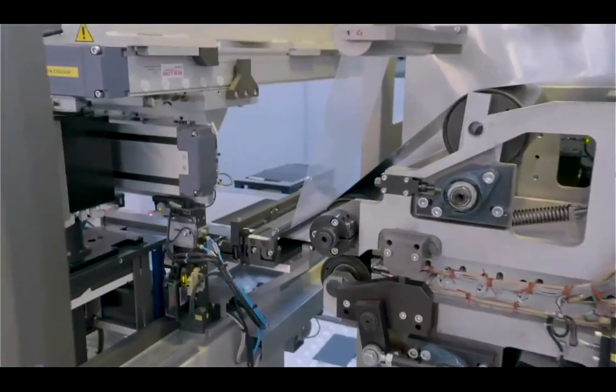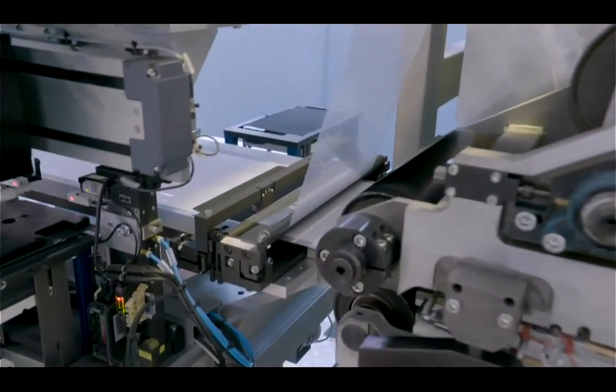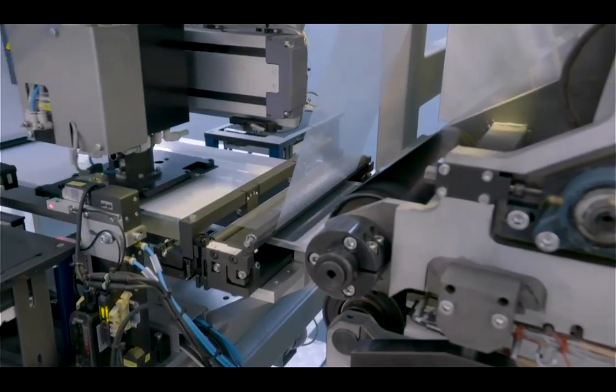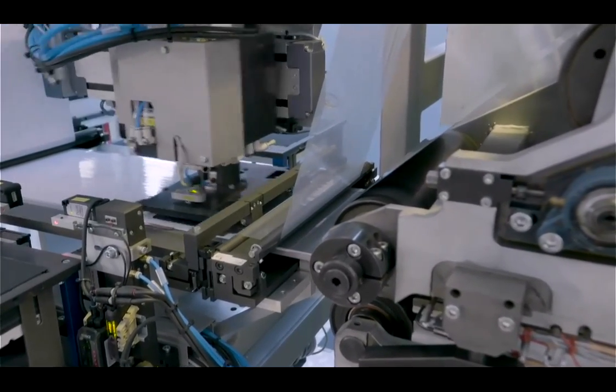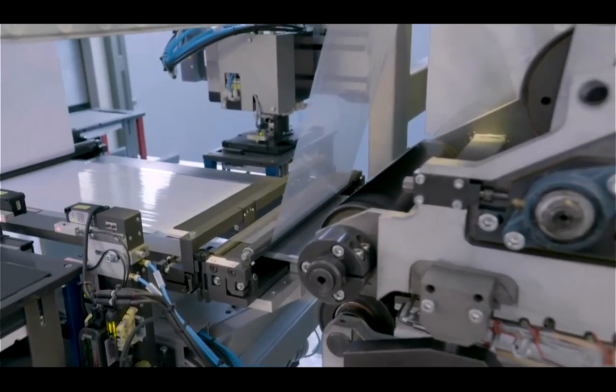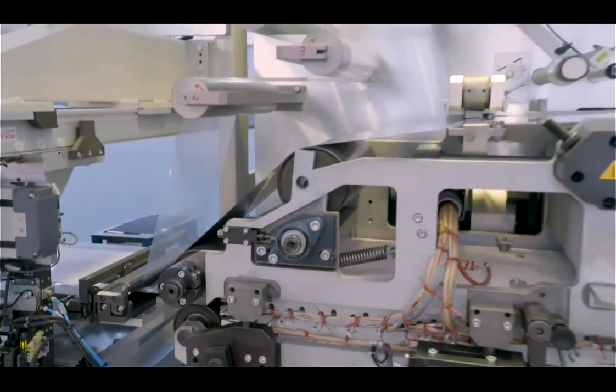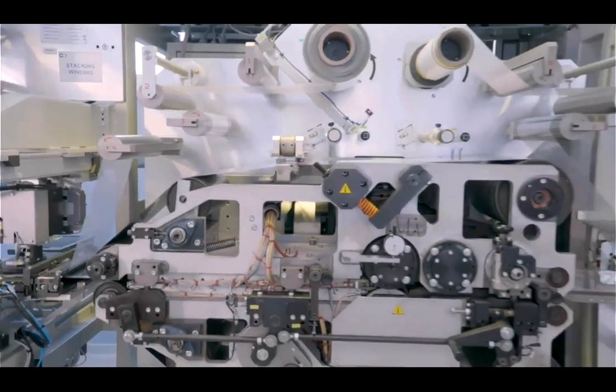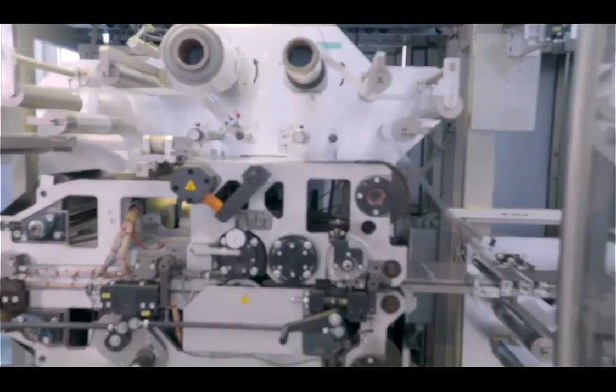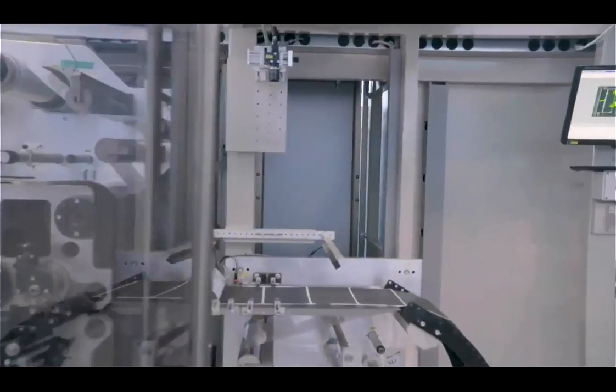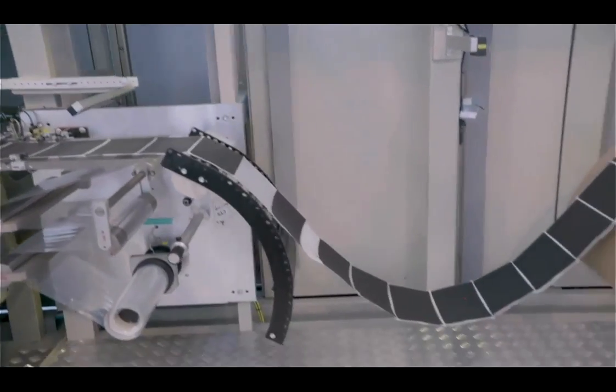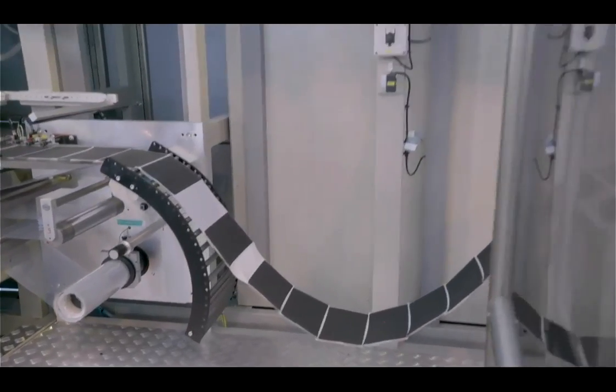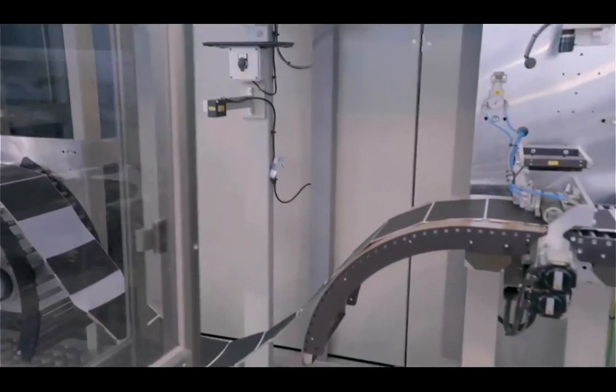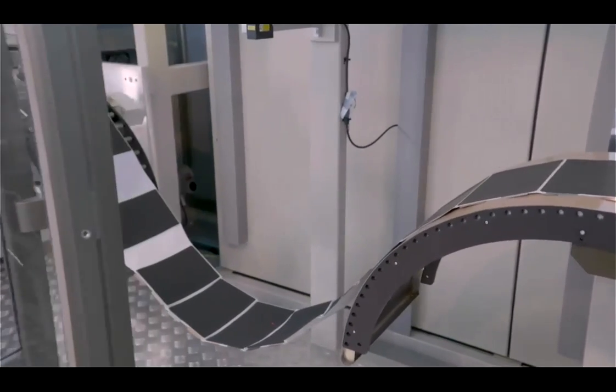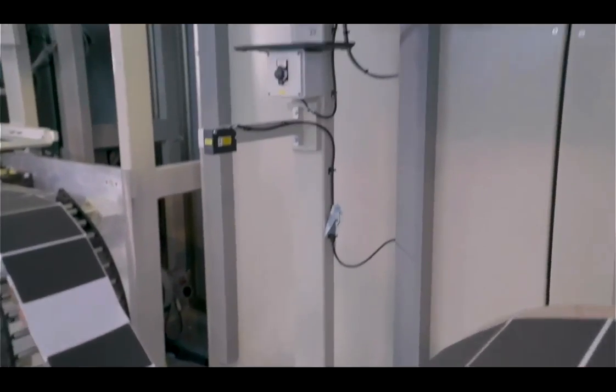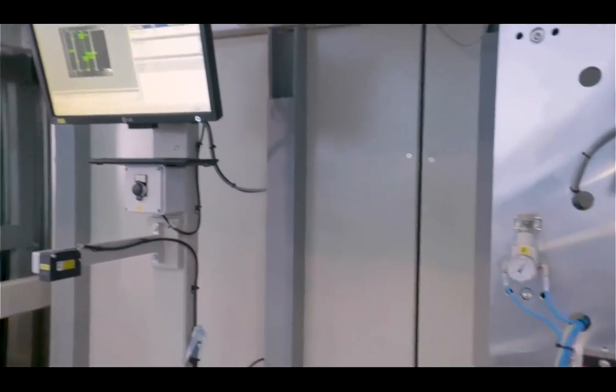Now you are seeing on your screens the lamination station. So with this station, what we do is apply a very light pressure and temperature to laminate the electrodes to the separator. To be able to do this, we have a special separator that has a very thin layer of PVDF on the surface. So now you are seeing all the electrodes laminated to the separator.